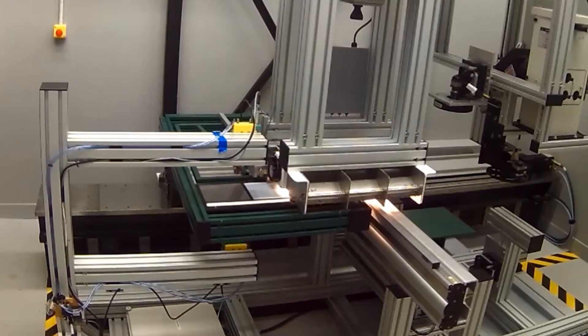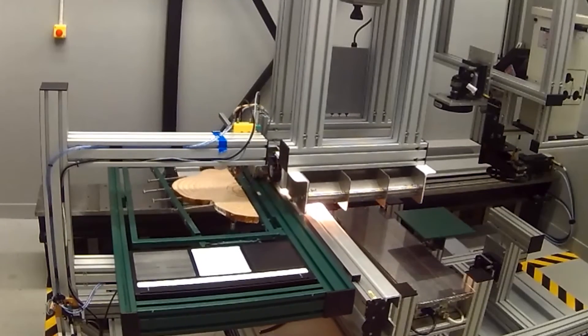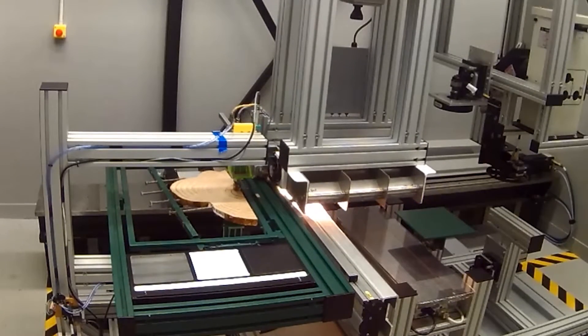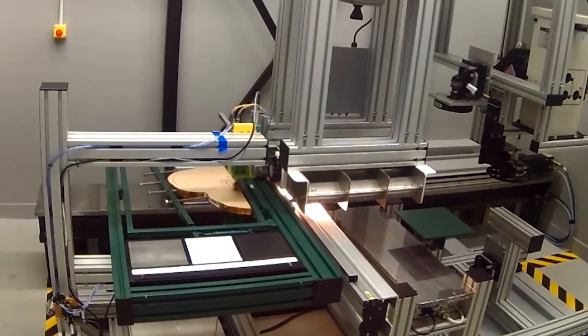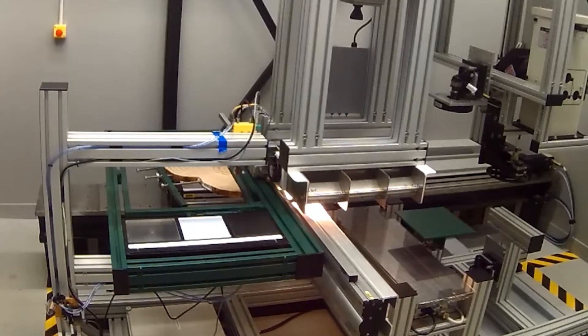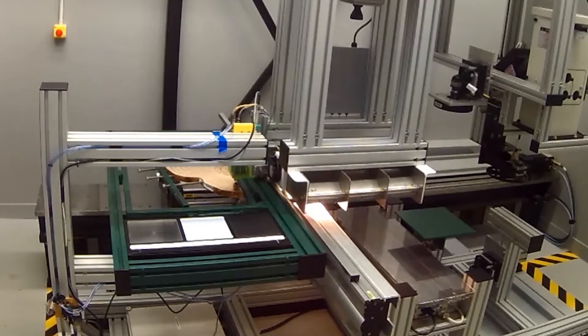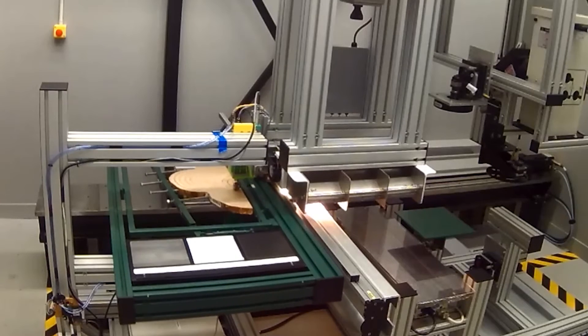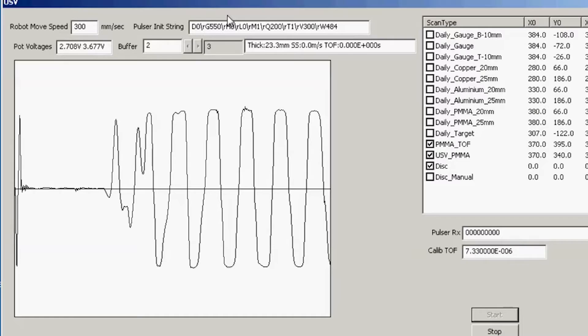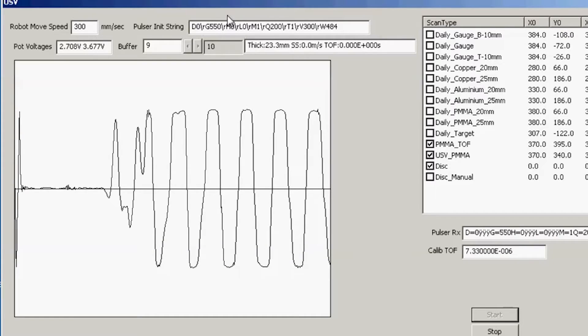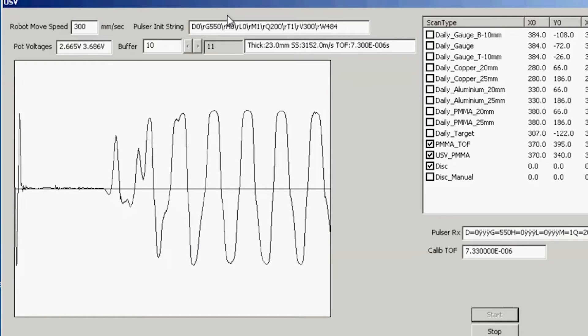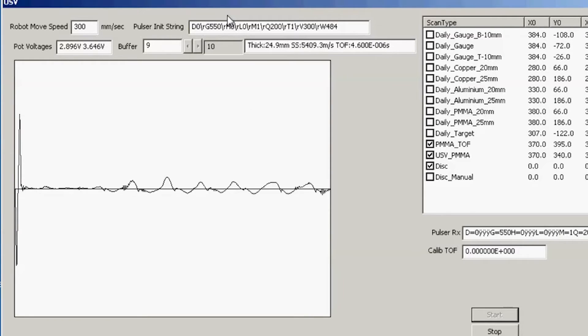Here the disc is being scanned between two ultrasonic rollers. These probes measure the speed at which an ultrasonic pulse passes through the disc. The velocity of the ultrasonic sound gives a measure of wood stiffness and allows the microfibril angle of the cellulose in the wood cells to be inferred.